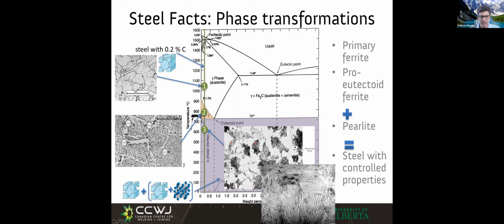So in this microstructure I'm showing you here, we have two things. We have the primary ferrite that came when austenite first started to decompose, and then we have this pearlite that is what came out when the remaining austenite transformed into ferrite and cementite together.